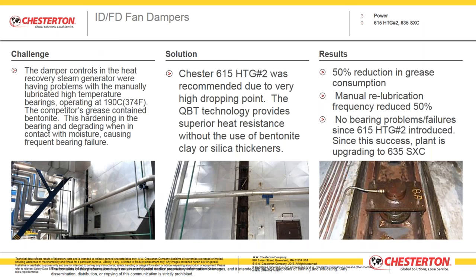But also the dampener control systems where the dampeners are fixed on a long shaft with two bearings. Typically, these things are running on the output, typically very hot, and require a lot of greasing because of the heat, in some cases up to in excess of 300 degrees Fahrenheit. And again, enhanced lubrication, looking at drop point, looking at oil separation, looking at thermal stability, and then allowing those three data points to help you choose a grease that is more able to handle the conditions. In this case, we were able to reduce grease consumption by 50%. We were able to extend the lube interval by 50%, and therefore we reduced grease, but also had a reduction of labor that was required to lubricate these things.